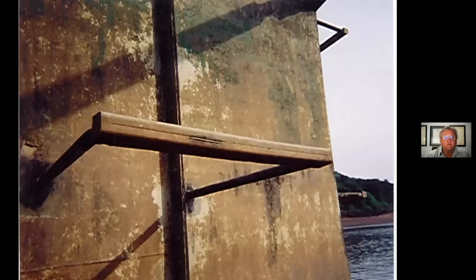Here's a good example of perhaps an incorrect anode selection because of the conditions to which it was exposed. You can actually clearly see the casting lines of these zinc anodes. And this is 5 years after they had been installed, and they've been permanently immersed for 5 years. And as you can see, they have hardly worked. So this is an example of an incorrect material selection.